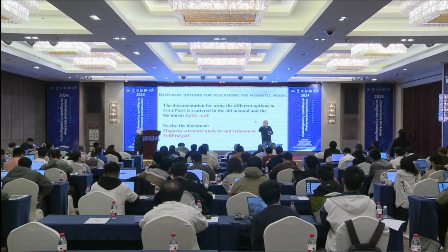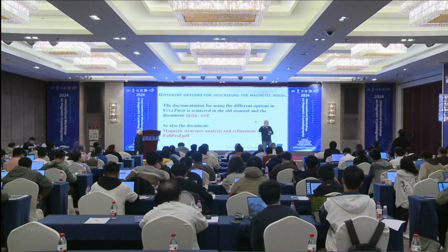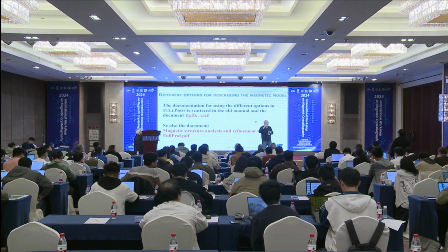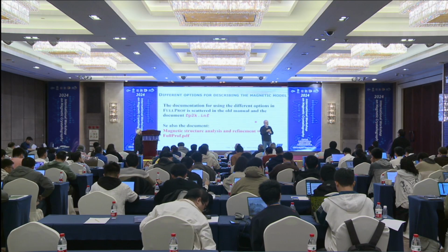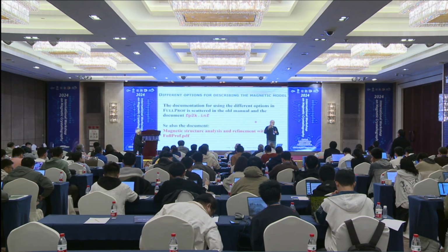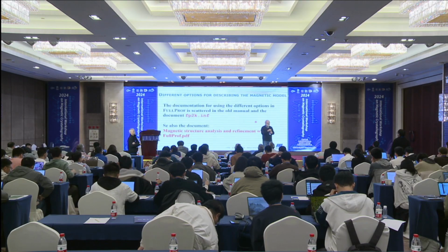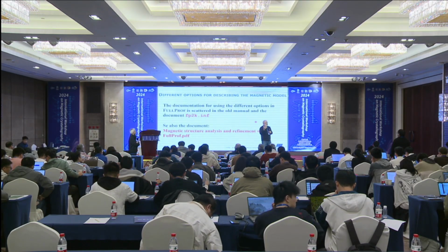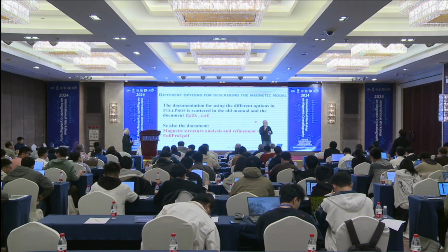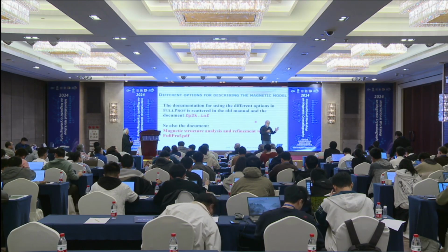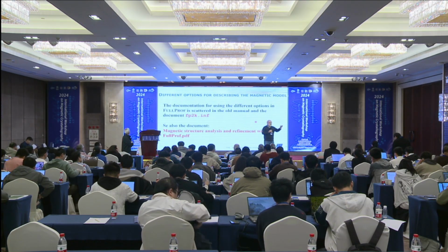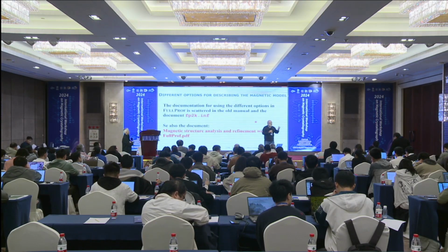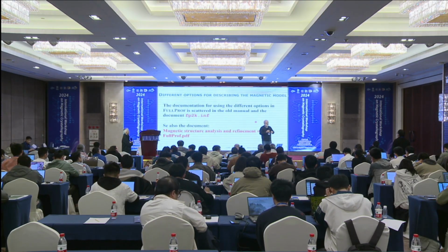But you have to put -1 in order to inform the program that you have to work also with -k, because it's not implied in the traditional way of working. You put -1 when you have a vector inside the Brillouin zone. When you use Fourier coefficients, many other things. When you use superspace, you put 1 or 2.